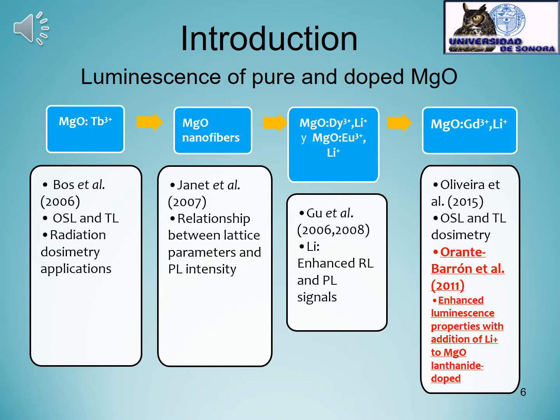Previously, we reported this paper on luminescent properties of magnesium oxide, which was produced by solution combustion synthesis and doped with lanthanides and lithium. In this case, we reported stimulated luminescence in general, which is radioluminescence, thermoluminescence, and also some TL dosimetry features, and we made a comparison between different lanthanides and the effect on these stimulated luminescence signals.